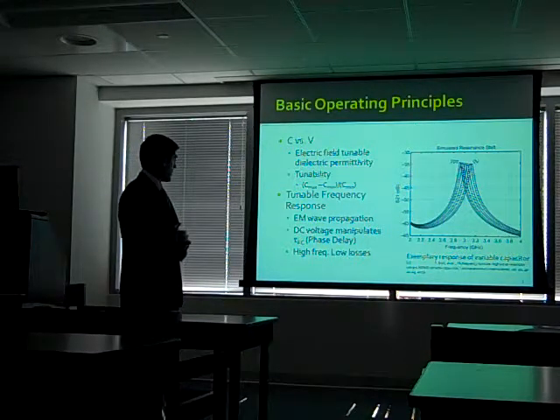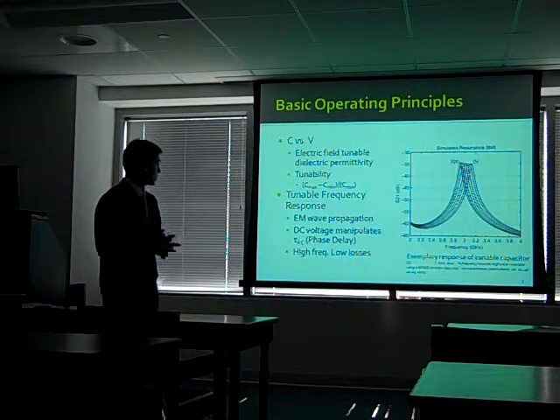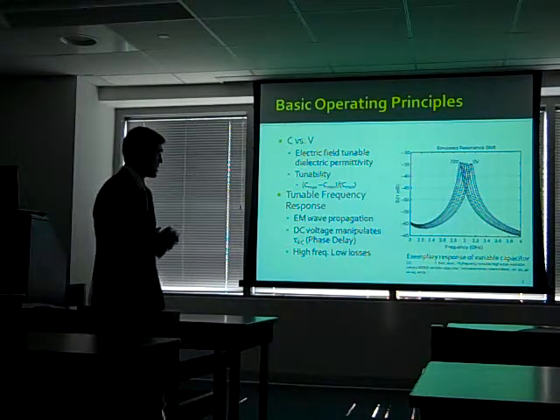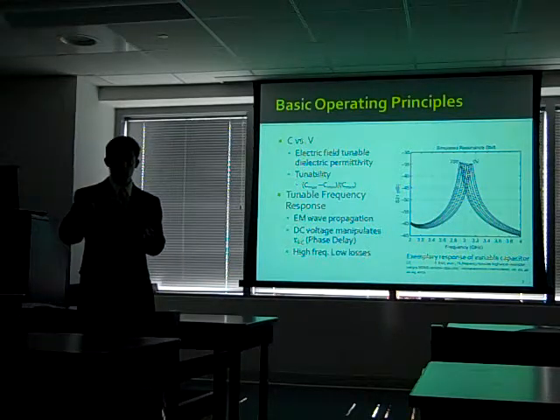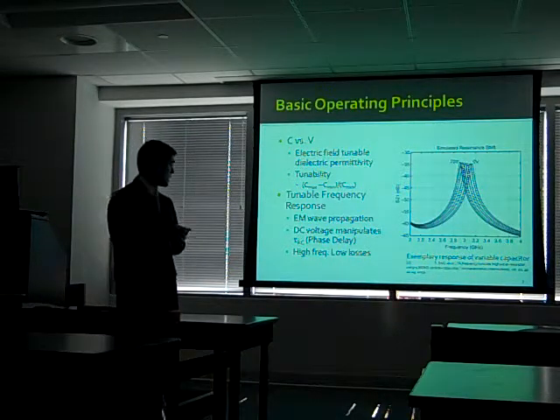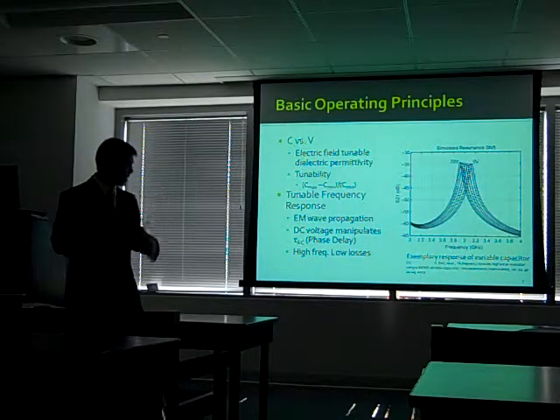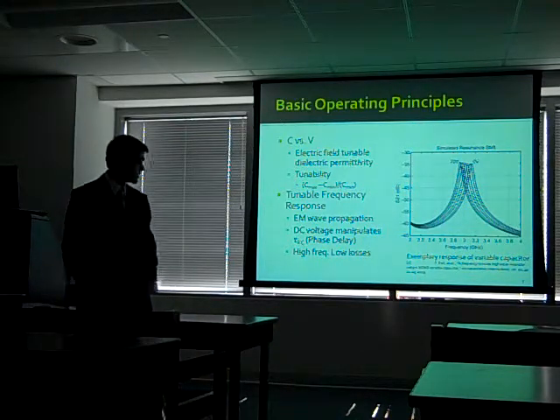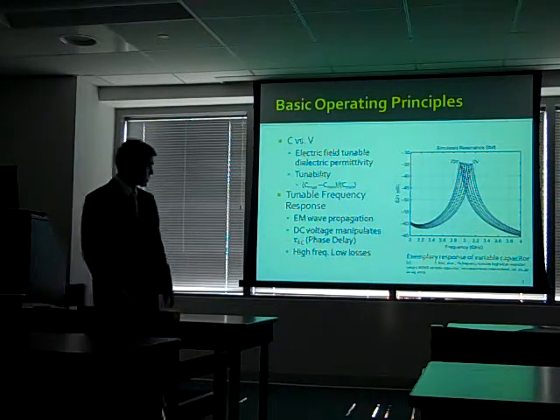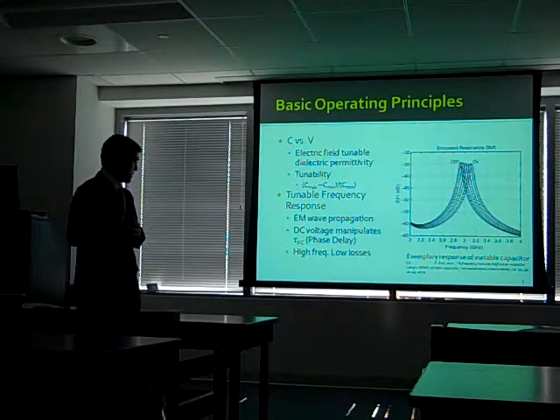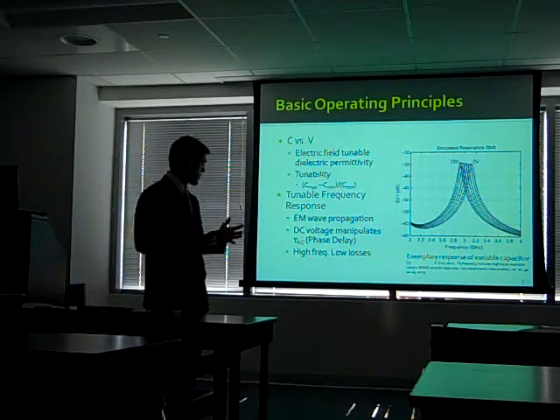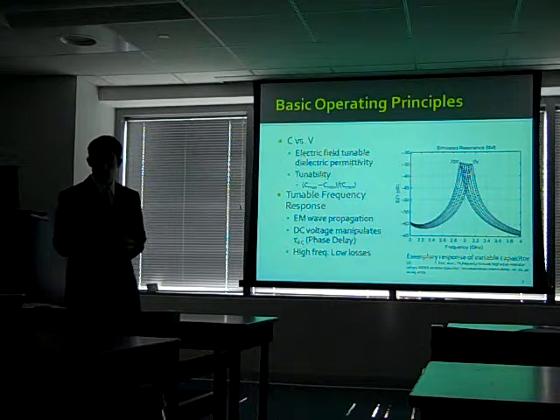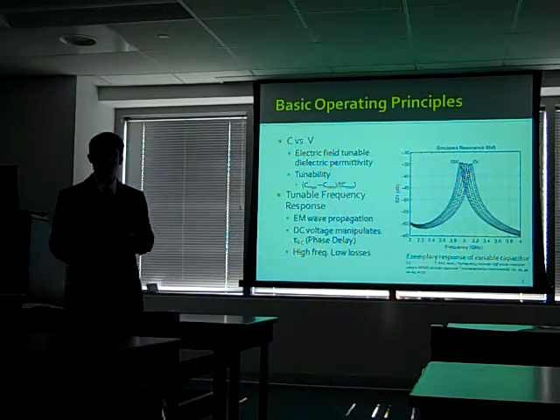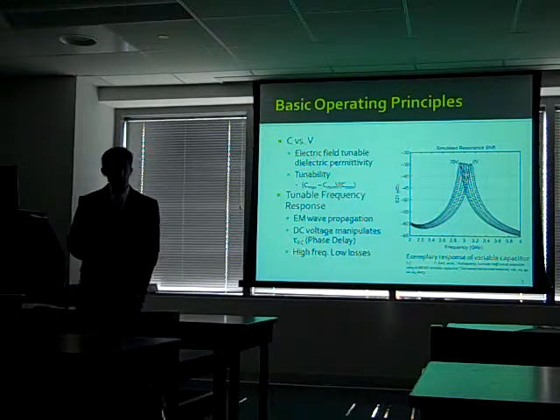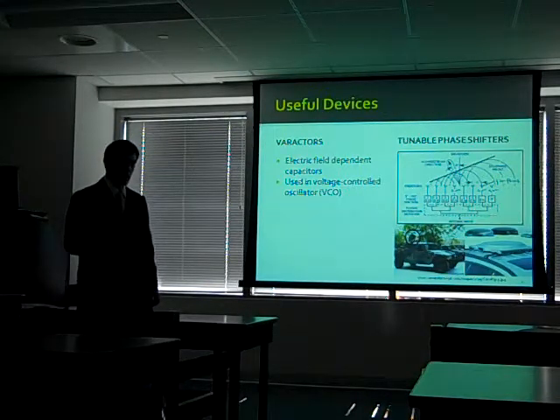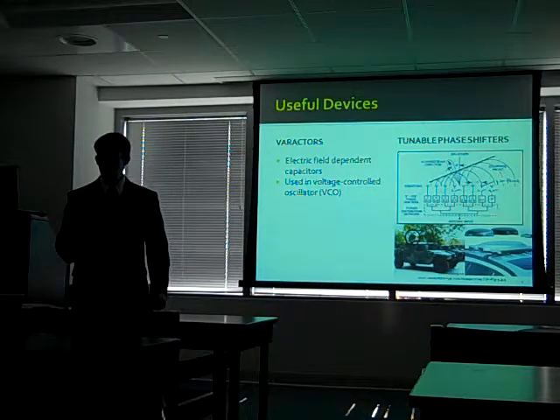Also, because of this behavior, you now have a tunable frequency response. So you can control the speed at which an electromagnetic wave propagates through the material. Or in other words, by applying a DC bias to your material, you can control the RC time constant of the device and introduce phase delays. And so we can make some interesting devices with that. In particular, graded ferroelectrics can do this at high frequency, even with low losses. So that makes them an important competitor to semiconductors and MEMS devices, which would also be used in these. So if we can do this with these thin films, then we can make some useful devices.